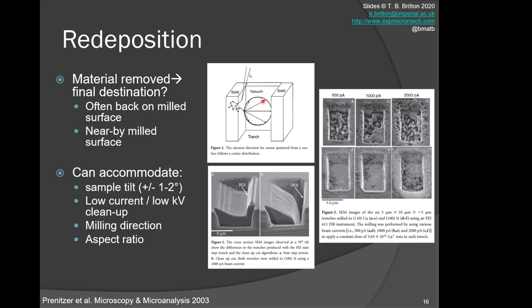As you do your milling, what will happen is you will get redeposition. Effectively, as you sputter, some of that sputter yield will redeposit. We can see this redeposition artifact where we have redeposition of material, and as we're sputtering, it will get redeposited sideways and build up this bank of material. Typically, for us to get good-quality surfaces, we can control how we do the sputtering.